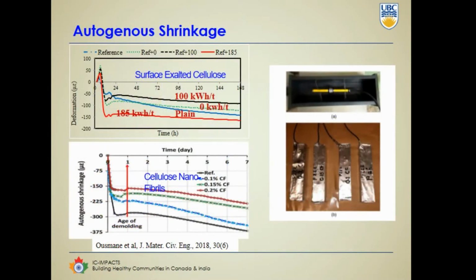Now, one typical test we do is called autogenous shrinkage. Remember, that's why I started. The concrete is going to shrink because of the low water-cement ratio. And here are some autogenous shrinkage tests. Here is your autogenous shrinkage with our material. This is 100 kilowatt hours. This is 0 kilowatt hours.